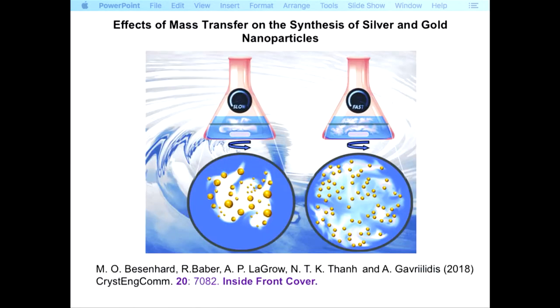So in a more recent paper we show that with some classical synthesis of the gold nanoparticle after Michael Faraday, we also have Turkevich in 1951, the very classical synthesis paper. But even then, now using the microfluidic, we can see that the mass transfer, how we stir the reaction fast or slow, will determine the monodispersity of the nanoparticle. So if you have a fast stirring or slow stirring, you have a different quality of the nanoparticle. So I just give you a flavor of some of the work.